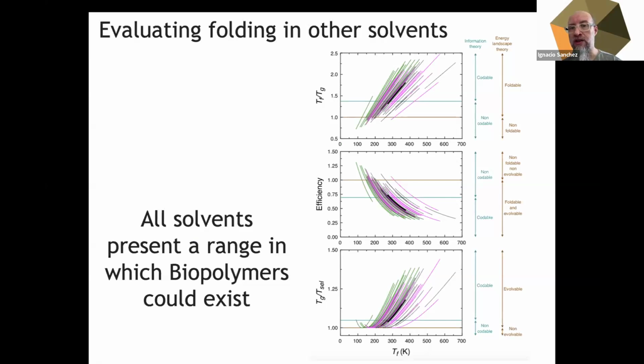For most of the liquid range, it is above the theoretical limit designated by the blue line. In the case of other solvents, all of it may be above the theoretical limit, only half of it, or only a small fraction of the liquid range. So solvents differ in how they fulfill this condition in their liquid ranges. We can do the same for the efficiency, checking that it's below the theoretical upper limit, and the ratio between the glass temperature and the selection temperature, checking that it is above the theoretical limit.